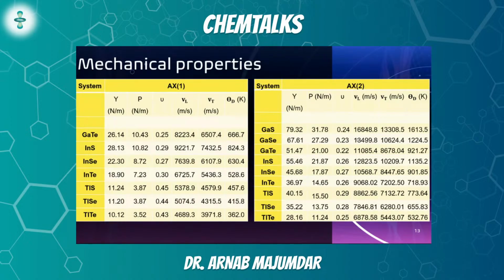Let's take, for example, TLSE. Or TLTE, the last one. The Young's modulus is only 10.12 for AX1, whereas it's 28.16 for AX2. And you can check for all the values. They will always be much lower compared to AX2. That means my second criterion of Slack, weak interatomic bonding, has been satisfied. So we have satisfied the first two criteria.